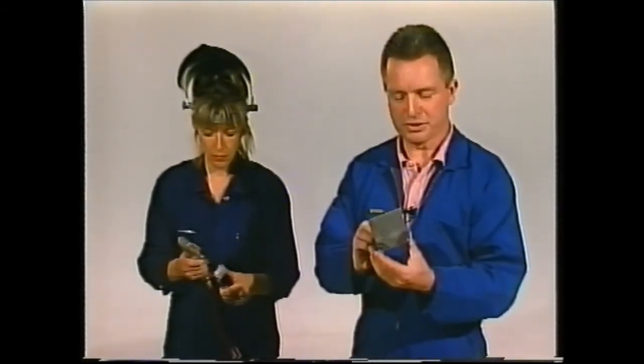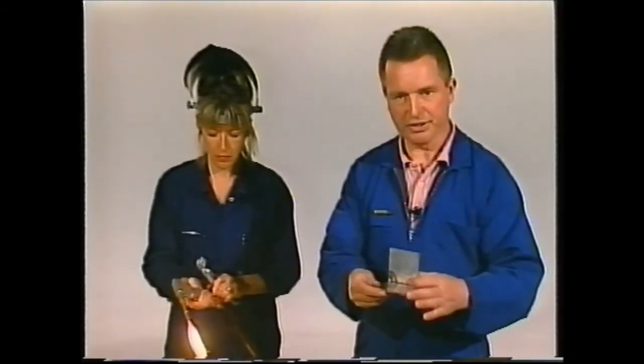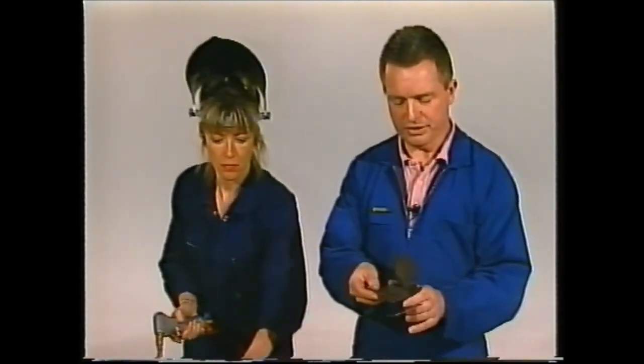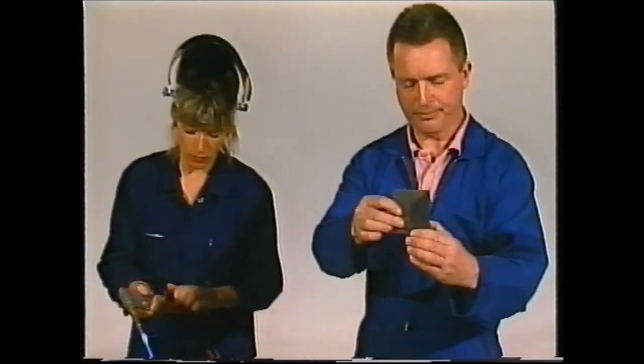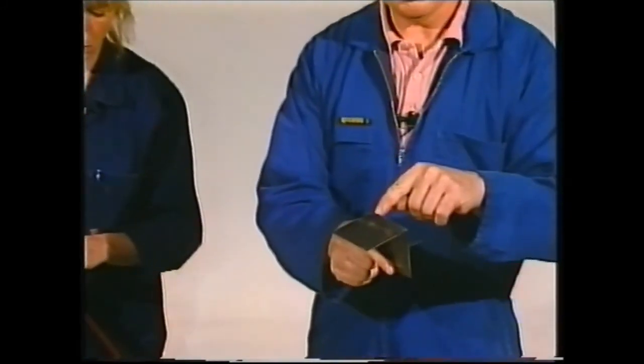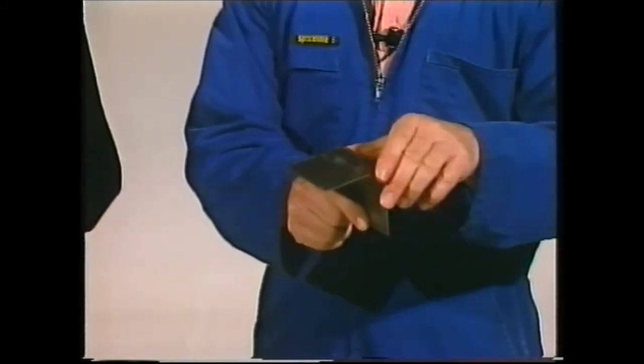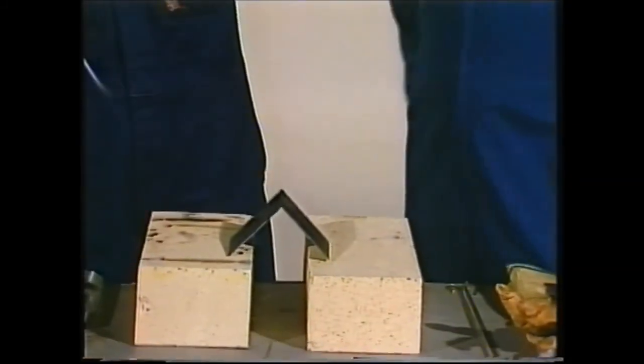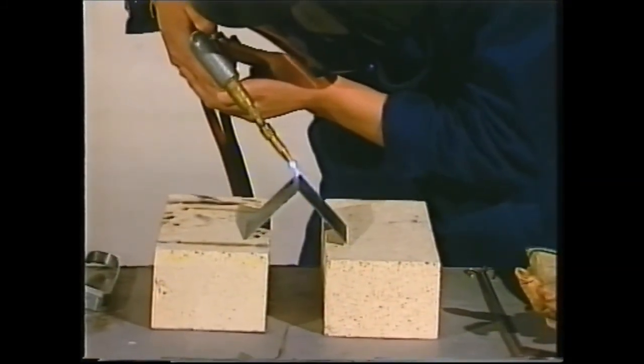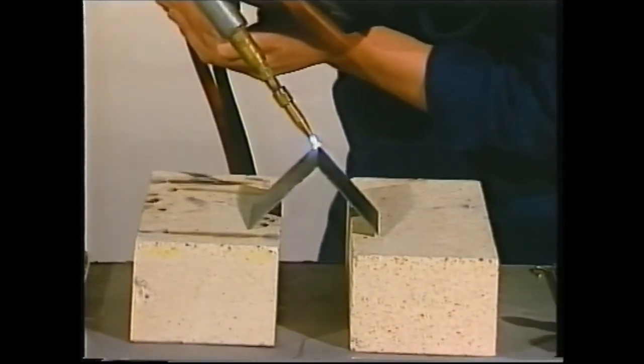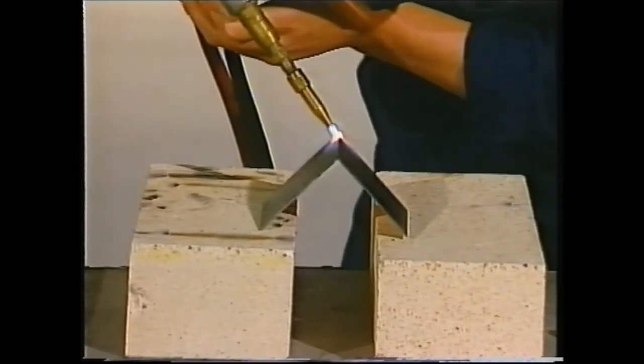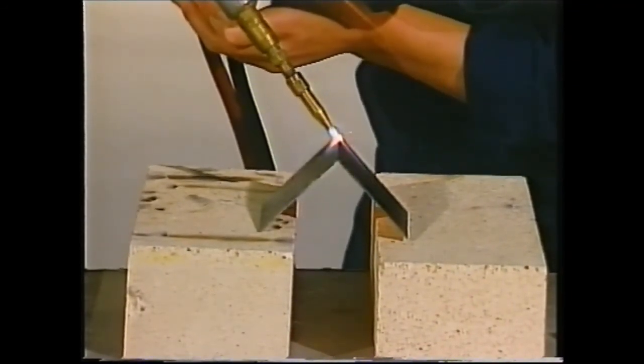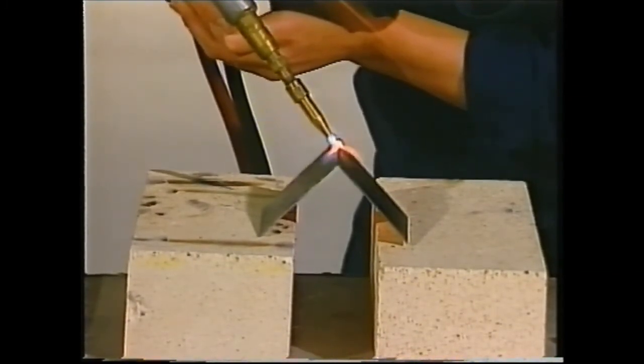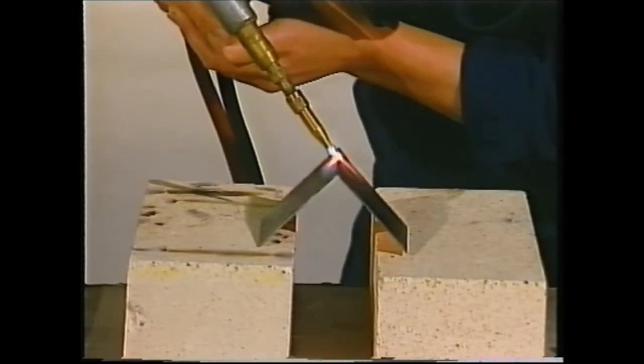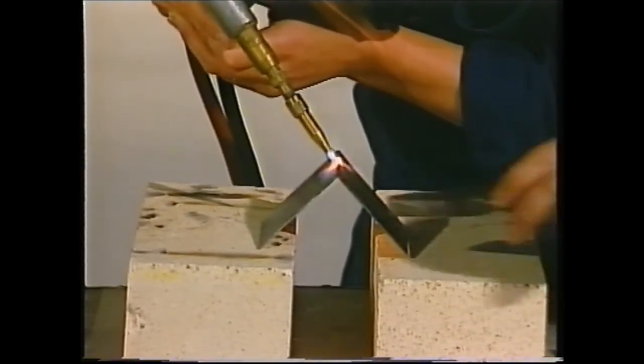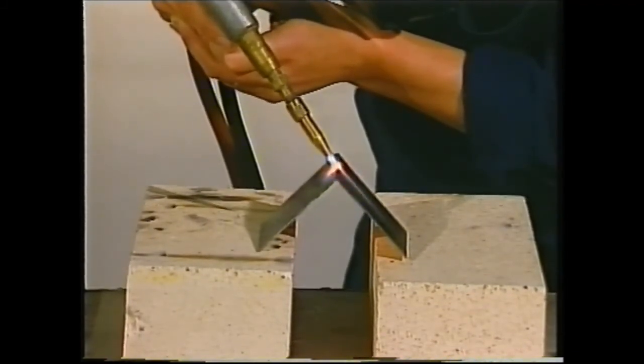We have here a piece of panel steel, and we've just tacked it together at a couple of points, and what we're going to do, or have done, is set it up nice and square, and then fusion weld the panel steel together, just to show you its lack of distortion abilities. Now, you'll notice straight away the very narrow concentrated heat pattern of the torch by looking at the red hot area. With a conventional oxy torch, you would have quite a large spread of the red hot, about ½ an inch either side. Now, what we're demonstrating here is that with a conventional torch, you would have these 2 legs lifting out in either direction and buckling all over the place.